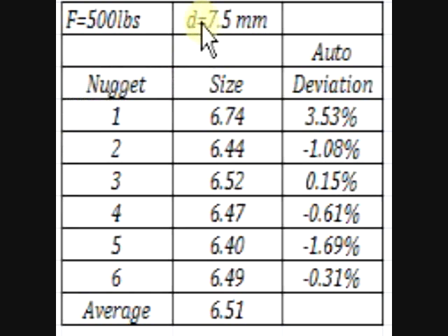We changed the weld cap from 6.5 millimeter to 7.5 millimeter. We expect to weld a bunch of welds which are 6.5 millimeter, 1 millimeter less than the weld cap area. We have to weld about 30 welds on the big sheets just to get the current adjusted to the right point, because the whole thing is designed to adjust only 100 amps per weld. And the result is 6 welds, average 6.51, which is 1 millimeter less than the 7.5 millimeter.